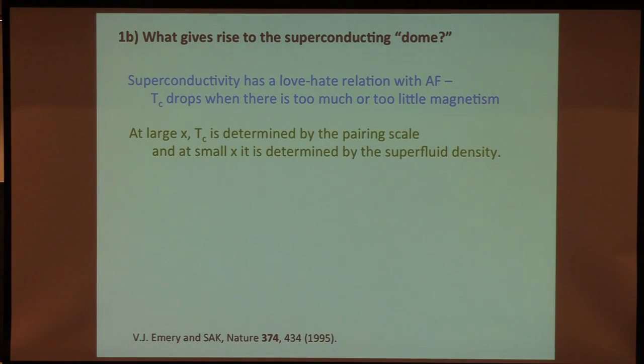But there's a somewhat more detailed understanding that you can have, which is that the optimal Tc is actually a crossover between two regimes, and that at large doping, far from the antiferromagnet, Tc is determined by the pairing scale, just as it is in conventional superconductors. But at small x, as one approaches the antiferromagnetic insulating phase, the superfluid density gets smaller and smaller, and so ultimately the superconducting Tc is controlled not by the pairing scale, but by the superfluid stiffness. So the way to think about this is to ask a different question than we usually ask: not, if I give you information about the normal state, how do I predict Tc? But how about if I tell you about the properties of the superconducting ground state of the system, and I ask you to predict Tc?